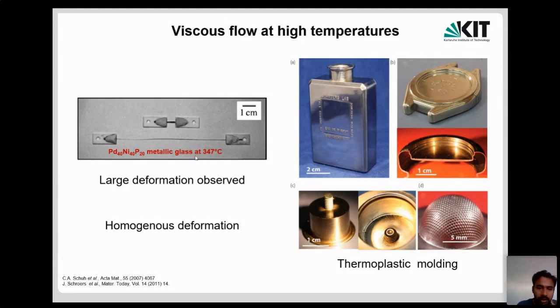So similarly, I told you metallic glasses have absolutely no ductility in tension. But above the glass transition temperature, you see this is a palladium nickel phosphorus metallic glass. And above the glass transition temperature, this dog bone specimen has deformed like 400%. So there is an enormous ductility here. So this is what is being used in these kind of components. If you see this,